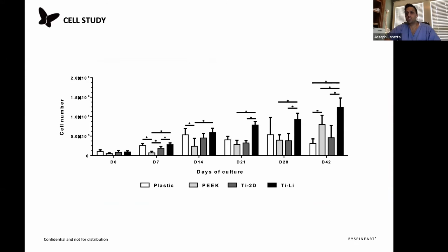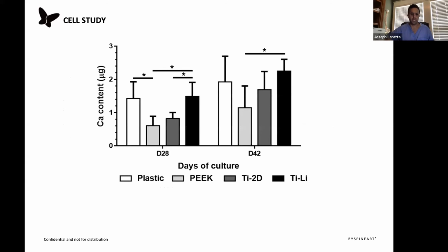This is the results of the cellular proliferation part of the in vitro study. So we looked at the number of cells and how they proliferated at different time points: 0, 7, 14, 21, 28, and 42. And what you can see is that at day 42, the 3D printed biomimetic titanium had the highest number of cellular proliferation. So there's something in the metal that is not only changing the structure of the cell, not only changing the morphology of the cell and the deposition of extracellular matrix, but it's also inducing cellular proliferation to an extent more than traditional titanium or PEEK.